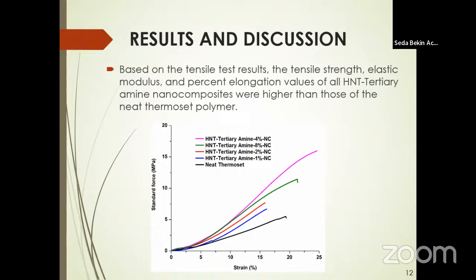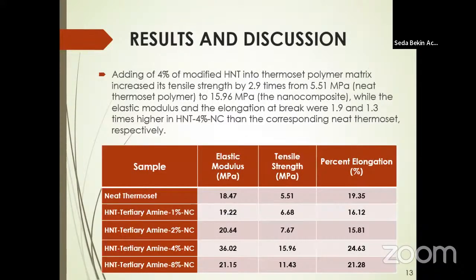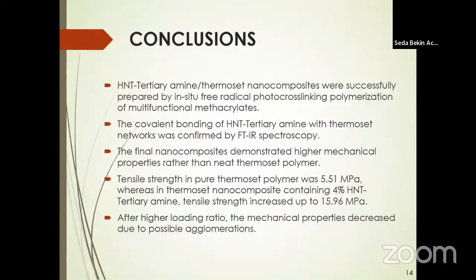Neat thermosets and thermoset nanocomposites containing different weights of halloysite were also investigated in terms of mechanical properties. Based on the tensile test results, the tensile strength, elastic modulus, and percent elongation values of all halloysite tertiary amine nanocomposites were higher than those of the neat thermoset polymer. As can be seen from the table, adding 4% of modified halloysite into the thermoset polymer matrix increased its tensile strength by 2.9 times, elastic modulus by 1.9 times, and elongation at break by 1.3 times compared to neat thermoset, respectively. So we can say that halloysite tertiary amine nanofiller increased the mechanical properties of the nanocomposites.